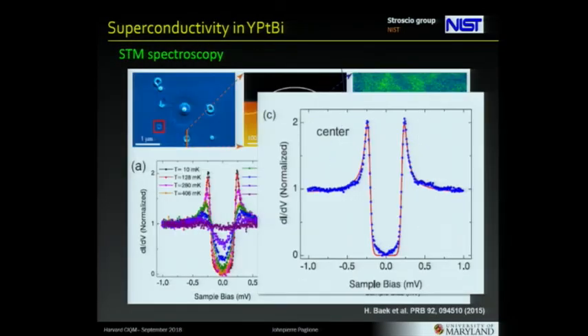Well, in the paper, he shows that you can plant in vortices one by one in this island. I'm surprised the penetration depth is a micron, two microns, you said. Again, this is visible by a proximity-induced island, so I'm not sure. So he's saying maybe smaller. That's weird. I would think penetration depth would be higher. So the short answer is they didn't see anything unusual about the vortex structures, or even the counting that you would expect to be unusual if it was an odd parity superconductor. But it was always limited by the fact that it's this island that's superconducting. It's not the intrinsic material.